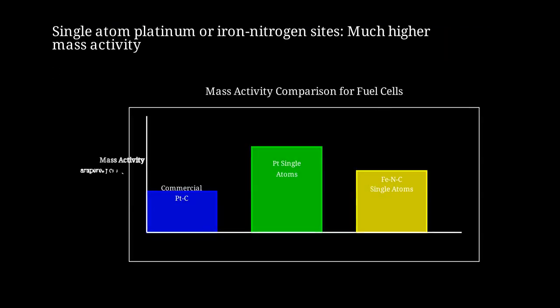Compare mass activity for fuel cell catalysts. Commercial platinum-carbon shows modest activity in blue. Platinum single atoms in green show more than double the activity. Even non-precious iron-nitrogen-carbon single atoms in yellow show competitive performance.